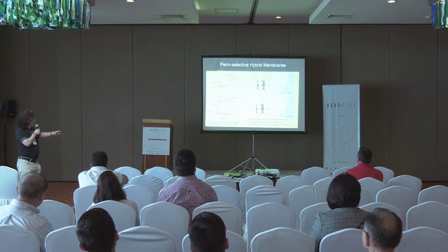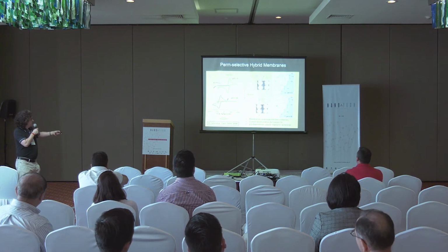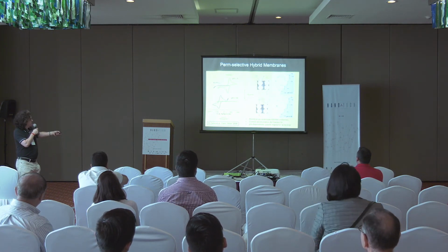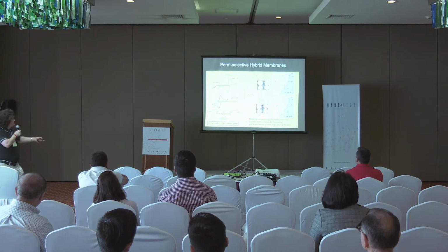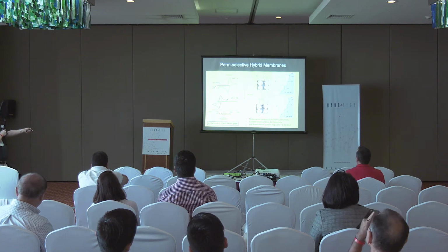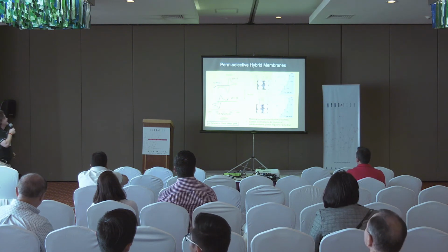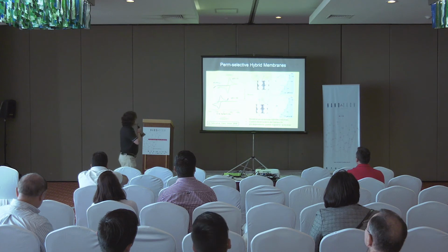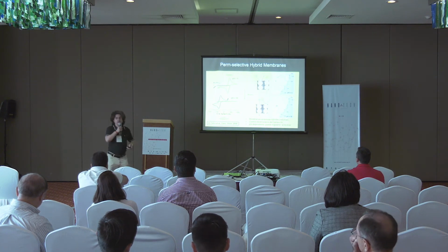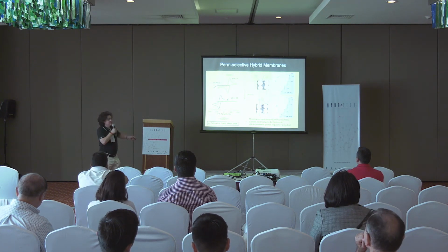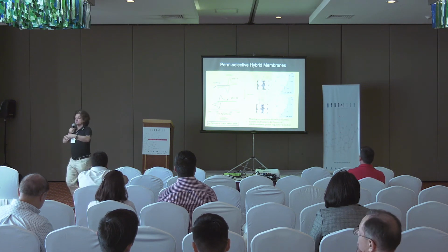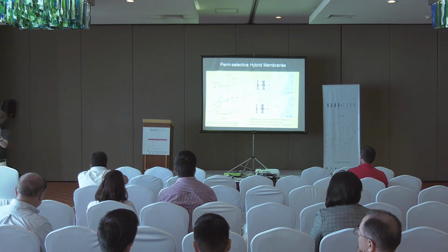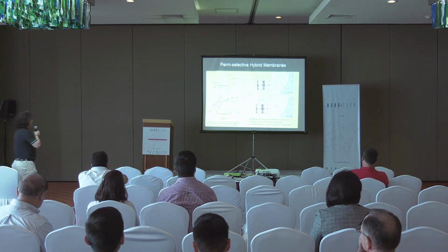At low pH, we have these positively charged groups. This is neutral or positively charged. So this positively charged surface electrostatically repels a positively charged molecule and exchanges a negatively charged molecule. And of course, the process is reversed at high pH, in which this and this species are deprotonated and now the pore is negatively charged. So nice, we have an ion perm-selective membrane.